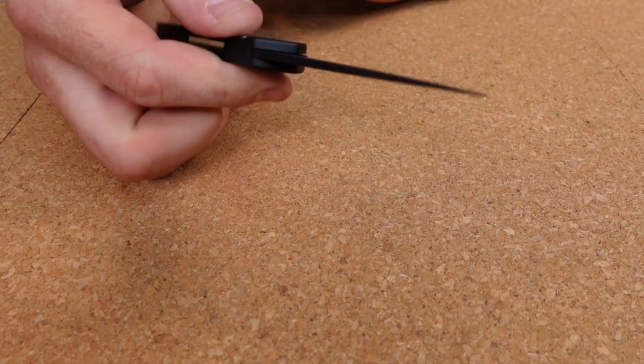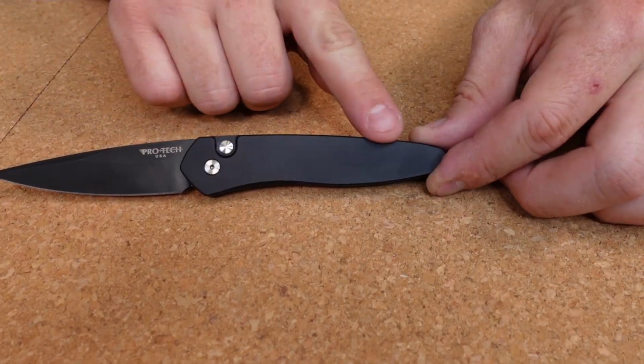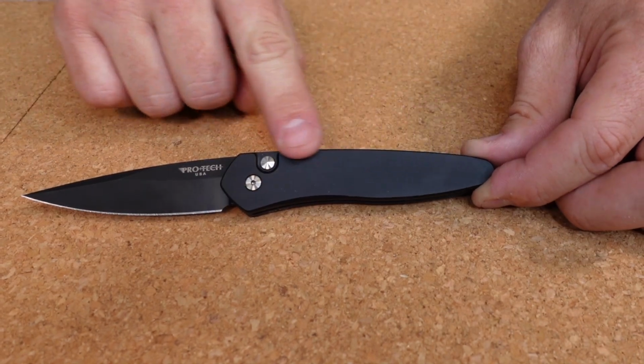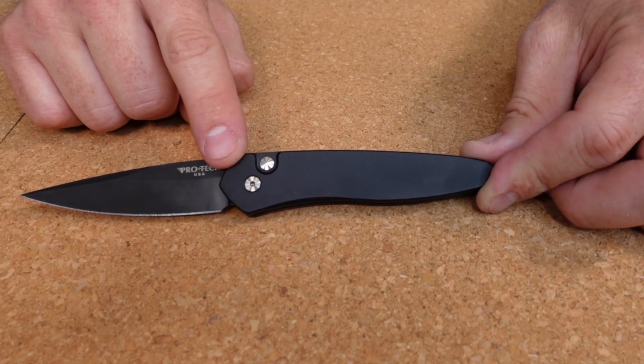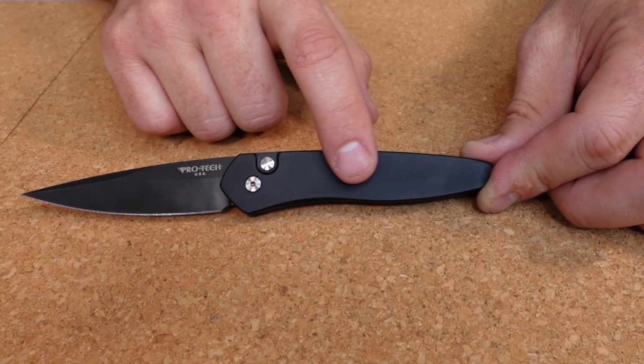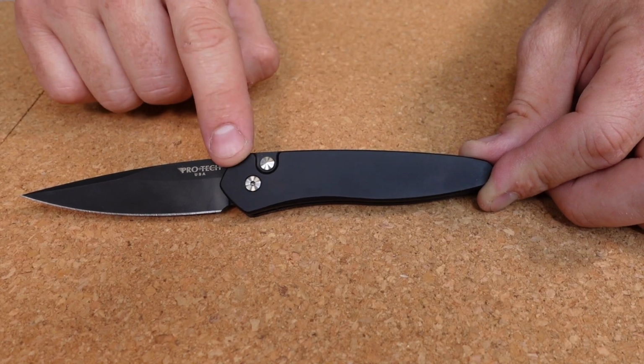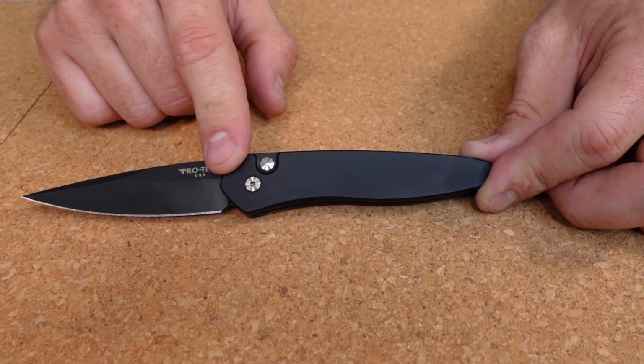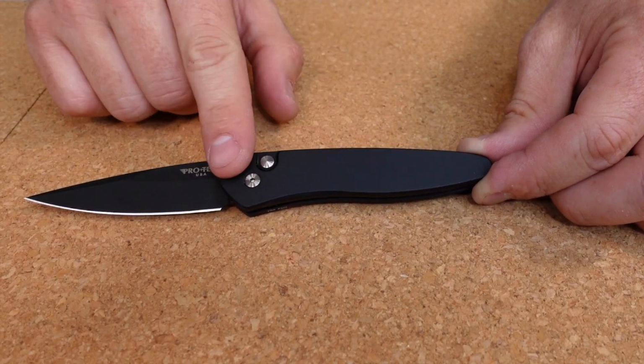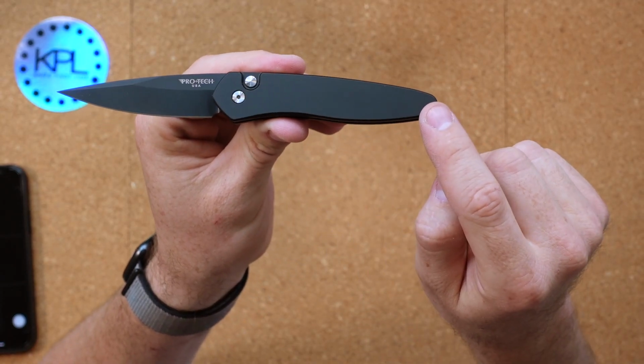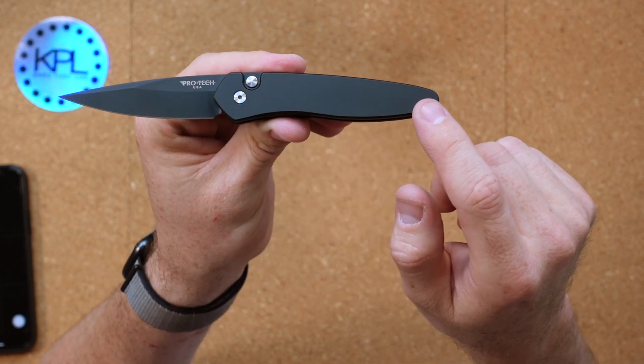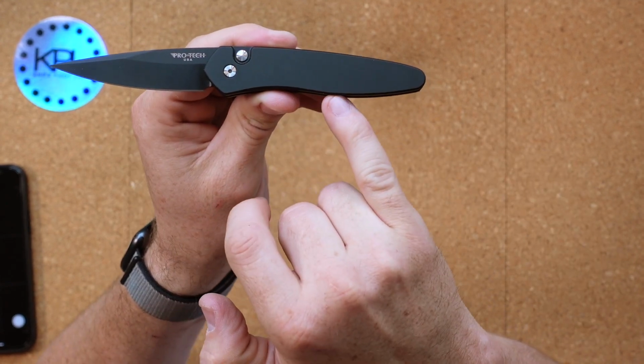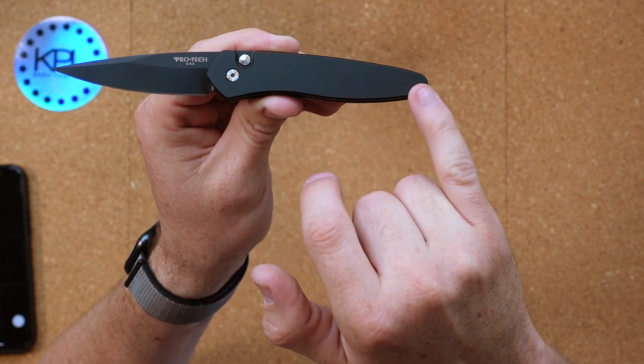It also has an advantage over titanium in that it can take a very hard surfacing very inexpensively. This knife here features a hard anodized coating, which is where, using electrolysis, an aluminum oxide layer is created on the surface of the metal. That's just the metal reacting with oxygen, kind of the same as rust with iron, but in this case, it is aluminum reacting with the oxygen to create aluminum oxide. That aluminum oxide coating is also extremely hard. We're talking about this aluminum oxide coating being in the class of materials that falls just under diamond on the hardness scale. It is going to be almost impossible to scratch the surface of this material with anything you're going to come across during daily use.